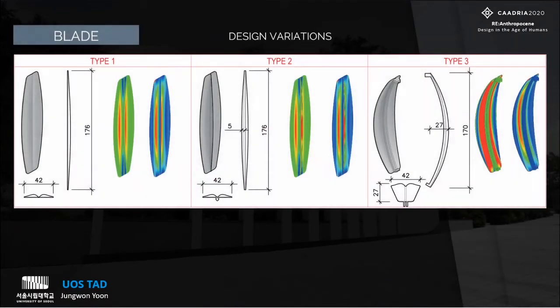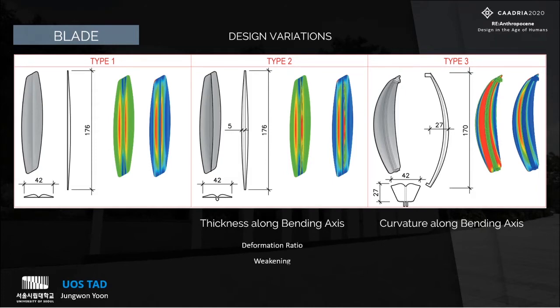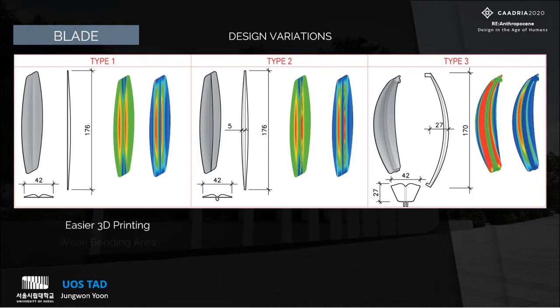First, blade. From our experiments, it was noted that the thickness along the bending axis would affect the behavioral performance and mechanical properties of the SMP model. Therefore, Type 2 was determined to test the thickness along the axis. Type 3 was designed to test the influence of curvature along the bending axis upon the SMP deformation and responses. As a result, the default Type 1 was easier to 3D print but weaker at the bending area. Type 2 was a version with a spine added to Type 1. In the case of Type 3, the curvature was added in the opposite direction from the bending direction.